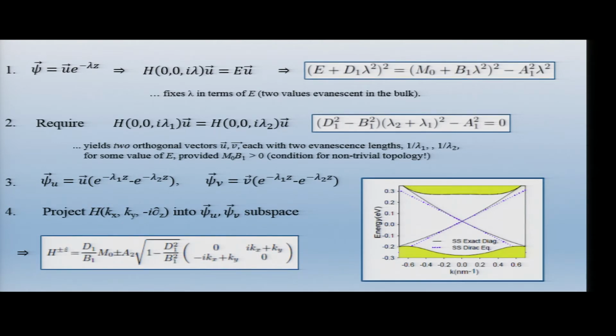If you actually compute the spectrum, that's these, I guess, these purple dotted lines over here from this Hamiltonian over here. You can compare this to the results from just simply taking a slab of the materials or the tight binding model that underlies all this and numerically diagonalizing it. And that's basically what's in the rest of the figure, these yellow areas, as well as the solid lines over here. And you see basically the match between the tight binding model and this simple-minded way of constructing surface states. They really match quite well.